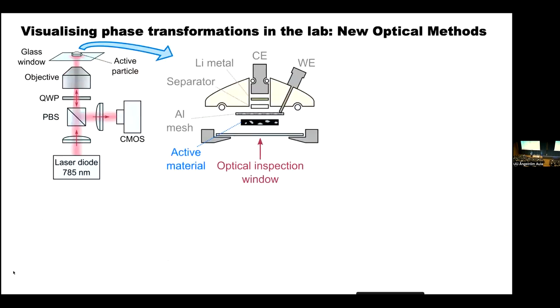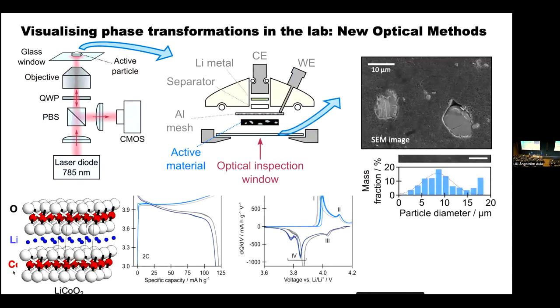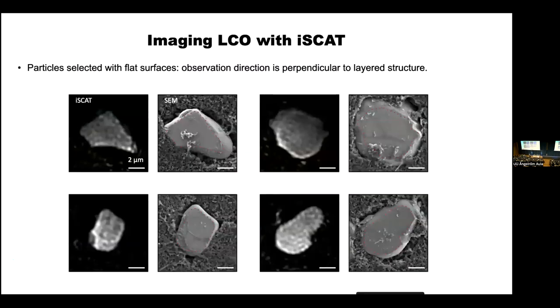So this was something that we set up just before the pandemic. To keep it simple, we took an L cell, a cell used typically for Raman microscopy. We shone a laser through it to an electrode. And just because I wanted very large, well-characterized particles, the obvious ones were lithium cobalt oxide. And you can see the lithium cobalt oxide basal planes distributed in this carbon matrix. And so these are some of the first images of LCO using this technique, iSCAT, not a particularly nice name, but there we are.